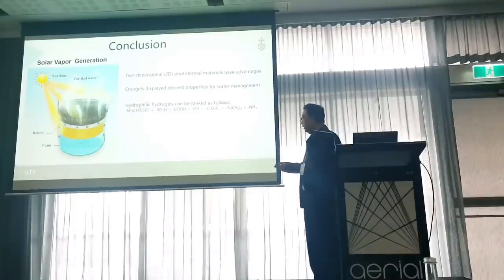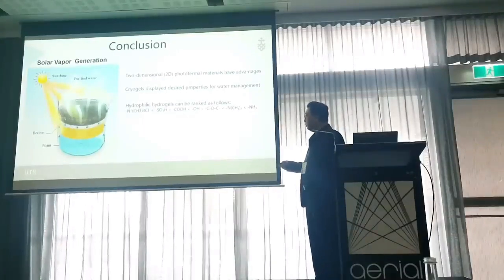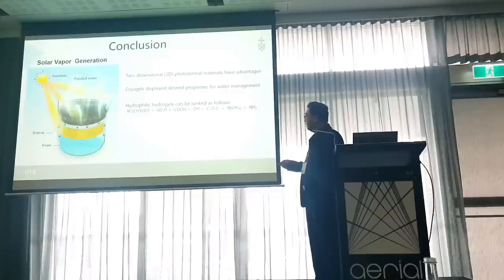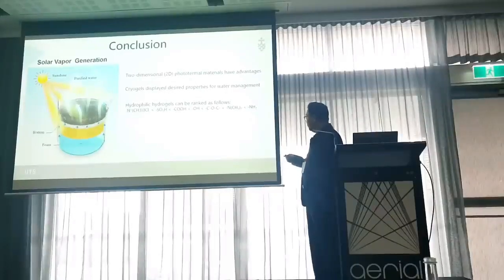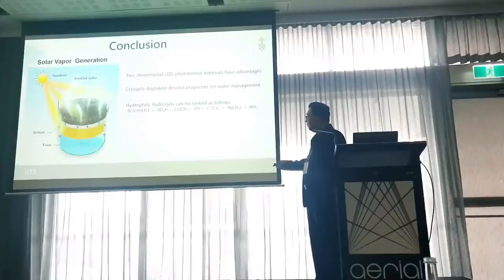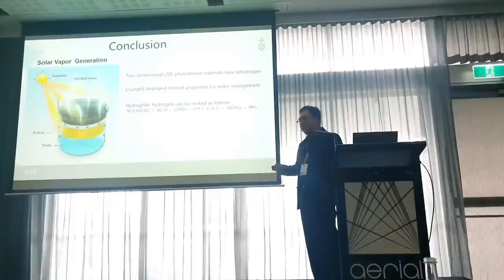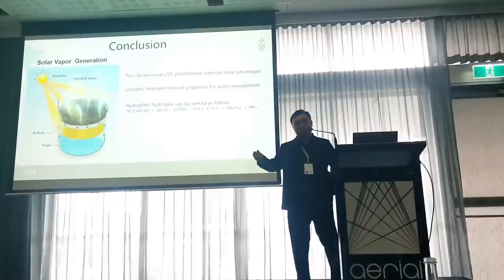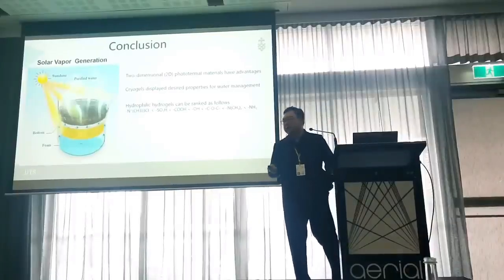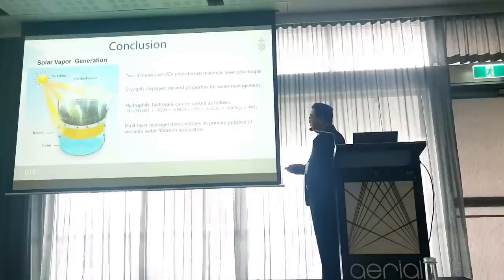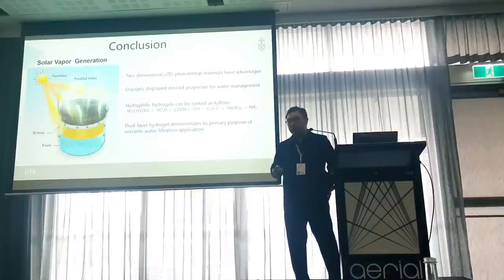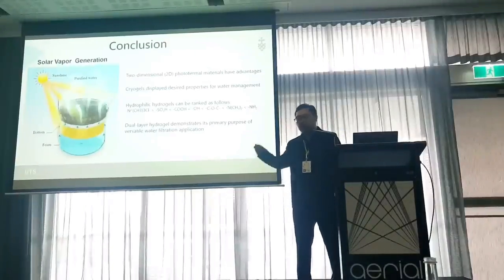Thirdly, we also investigated the hydrophilic groups, and the hydrogels can be ranked in terms of their HVD performance. The amine group shows the best HVD performance, but the ammonium group shows the lowest HVD performance, and we demonstrate that the chemical structure of the hydrogel can also affect HVD performance, not just the physical properties. And finally, we developed this novel dual-layer hydrogel and demonstrate that it is multifunctional. It can enhance the heat insulation, kill bacteria, and show a very high salt rejection effect.